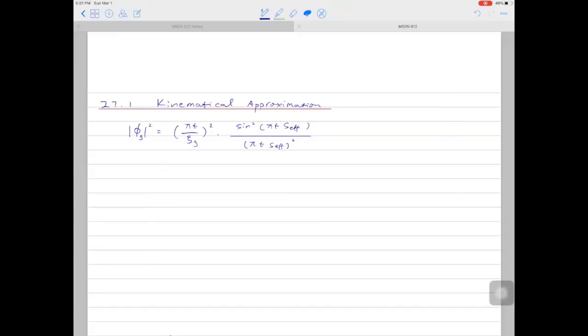Let's revisit what we learned in the dynamical contrast. Start by looking at the solution of the Howie-Whelan equation. Phi g square tells us the intensity of the diffracted beam. The effective excitation error can be written as a function of s, the excitation error, and ξg, the extinction distance.